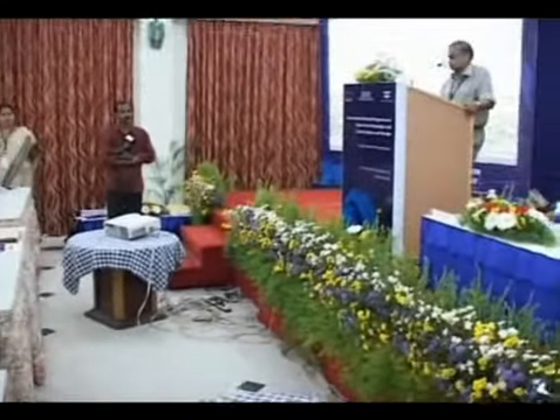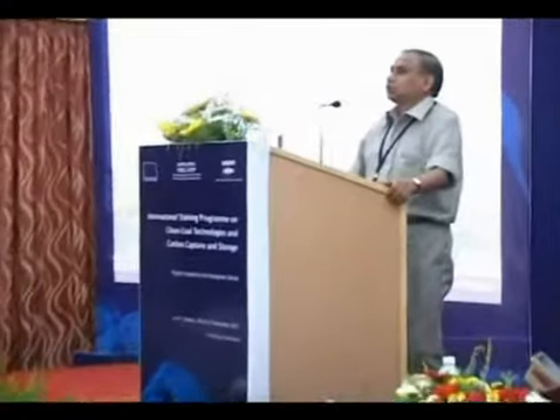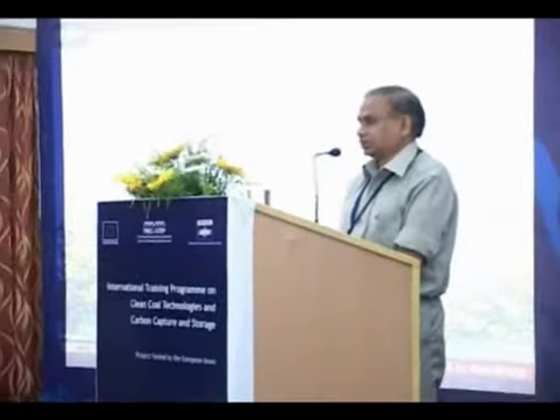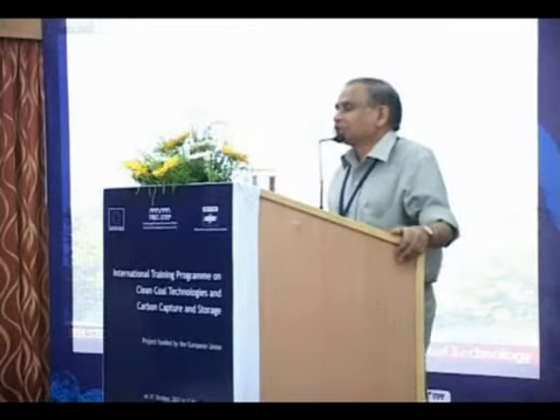In Neyveli, when we put up the 4 into 210 megawatt plant, and when the 3 into 210 megawatt transfer plants went into operation, there was a specific problem encountered. There was FeS2 present in the marcasite, and marcasite has a tendency to lower the initial deformation temperature of the ash. When the fuel was given to us for design, it was about 1070 degrees initial deformation temperature. But when the boiler went into operation and it was assessed at Stuttgart University, it was about 850 to 900 degrees centigrade.